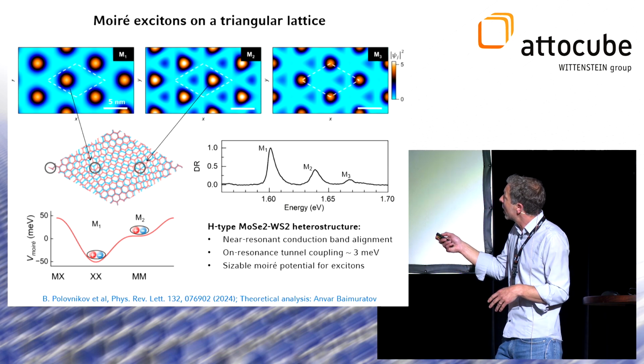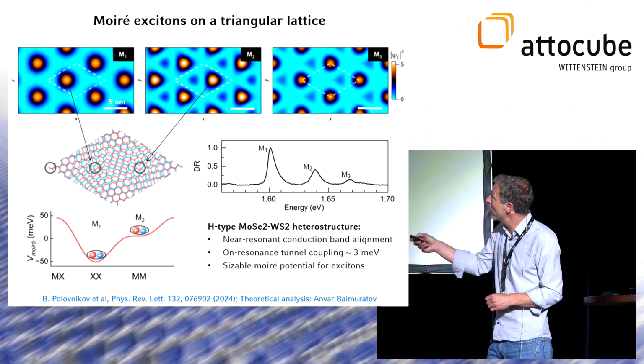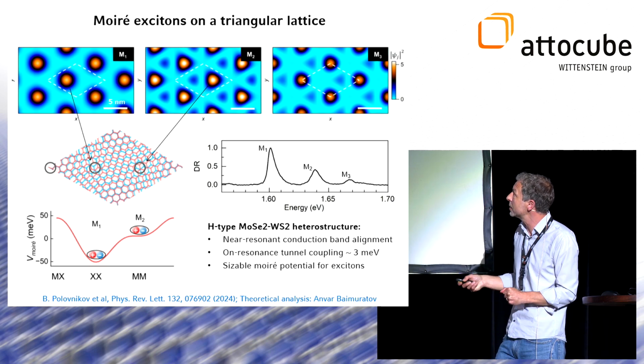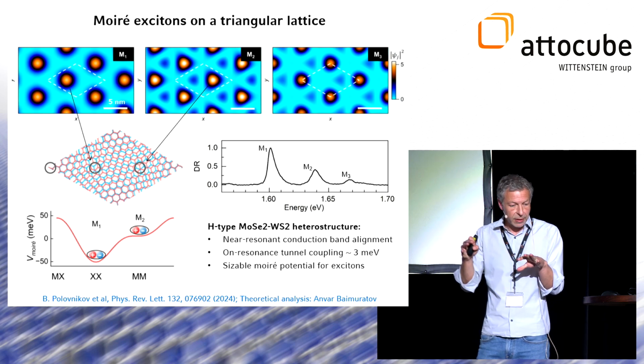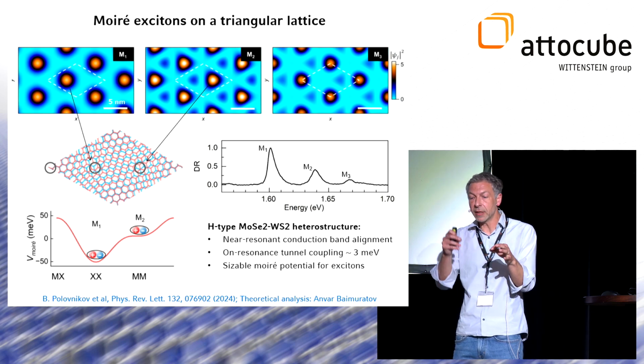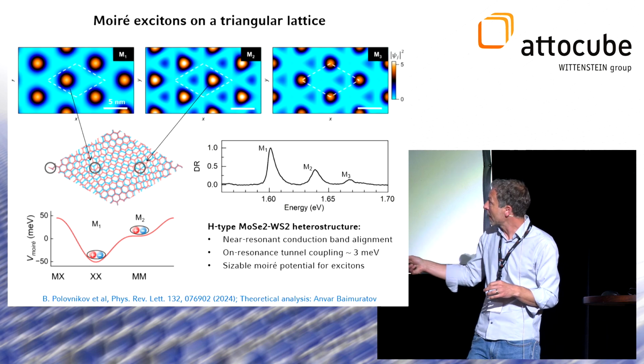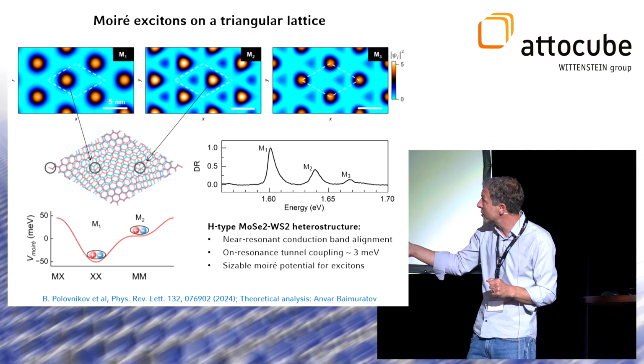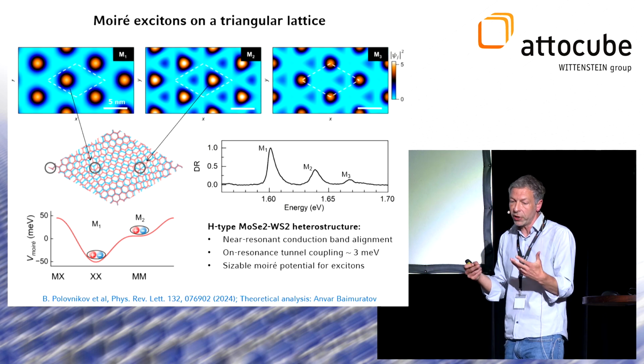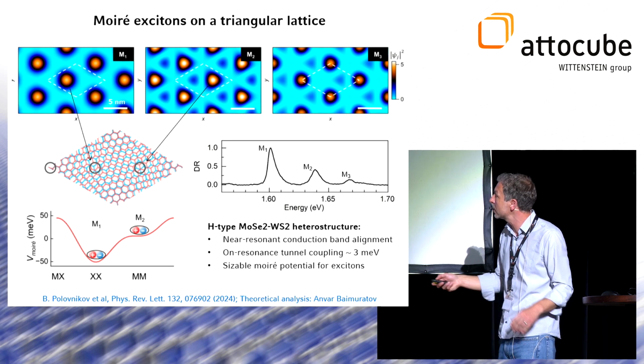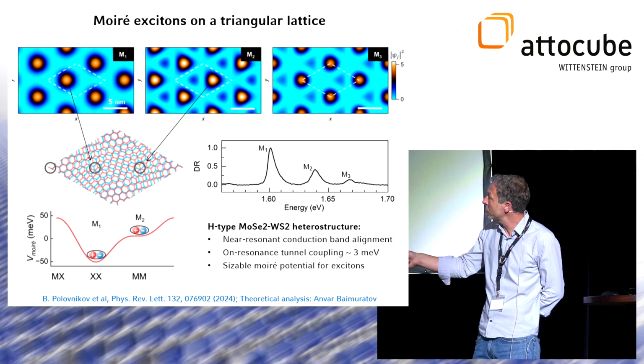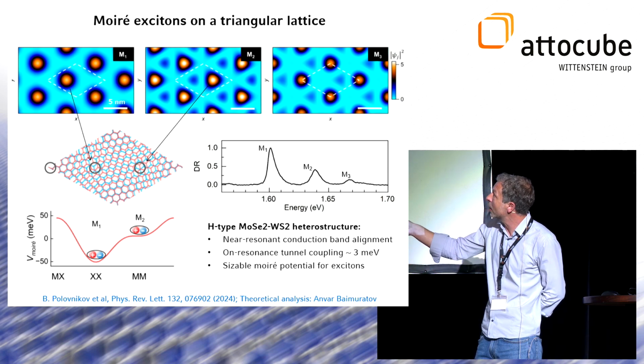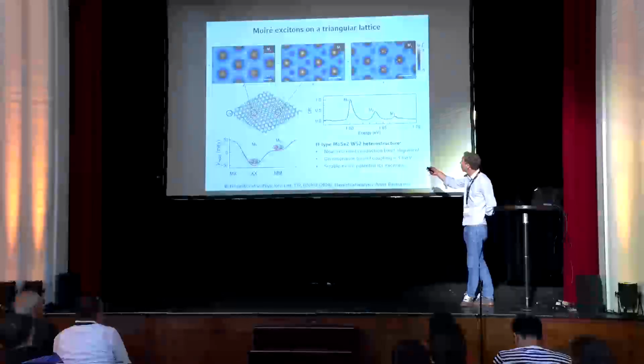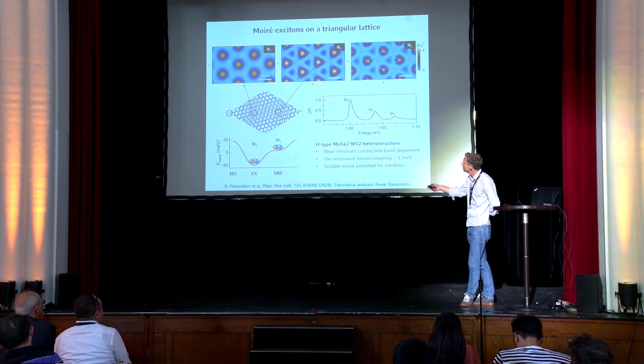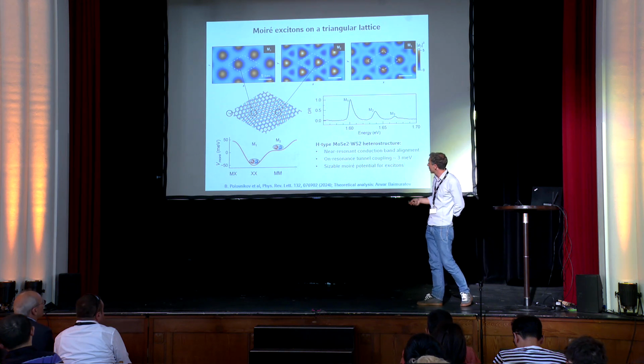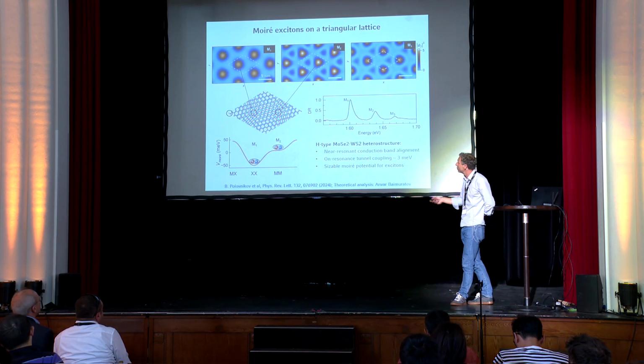And we can construct exciton wave functions for all these 3 moiré states, indicating that they are distinct in their interlayer character, but more specifically in the position that they reside on the lattice. So this is how a moiré heterostructure builds up an excitonic lattice, right? And the lattice differentiates between the position of the moiré peak 1 with maximum wave function from a moiré peak 2 whose home is displaced from that of M1.